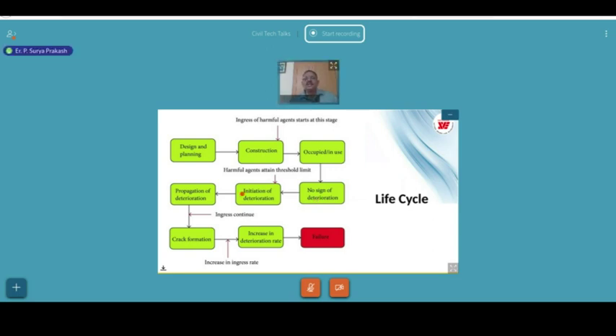Then there will be initiation of deterioration. That means in our limit state, we allow cracking, and through the cracks or through the porosity of the concrete or through the honeycombs that are left without treatment, without protective coat, there will be harmful agents attaining threshold limit in the structure. Then propagation of deterioration, and then crack formation, which is physically visible. Otherwise also there will be cracks in the concrete. And then increase in ingress rate and increase in deterioration and then failure. So this is the life we are talking about.